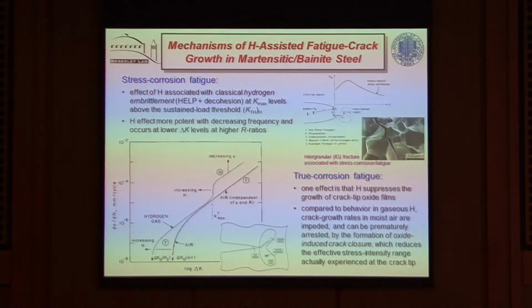Now, there is another effect that's interesting, by the way. If you look at lower delta Ks, you see hydrogen also accelerates crack growth down here. And what's interesting, in these sorts of steels, where the mechanism is primarily decohesion related, the hydrogen-assisted cracking here is intergranular, but down at these lower delta Ks, it's not. It's transgranular still. And in fact, these lower growth rates are very important because they can dominate a life prediction calculation.